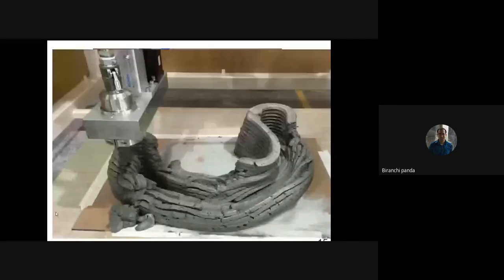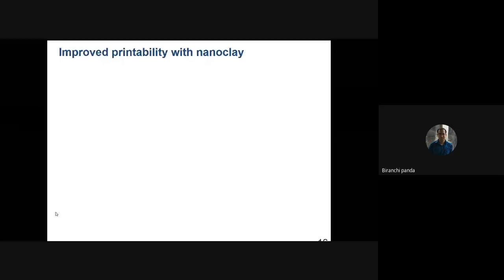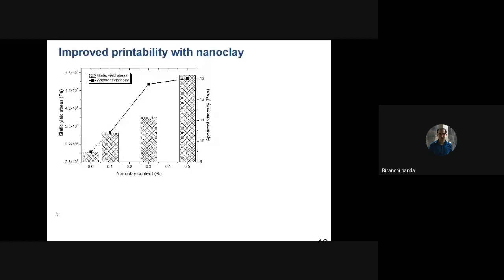So to improve this material combination, we tried to take the help of nanomaterials. Though they are nano sized, they can do a very wonderful job. So we used a customized nano clay. We made this nano clay. So what happens with this nano clay? We came to know that just by adding 0.5% of this nano clay to the mix, it can improve the yield stress or viscosity of the material 5 times compared to the control mix. So we found a significant improvement when we added these nanomaterials to this fly ash mixed concrete.